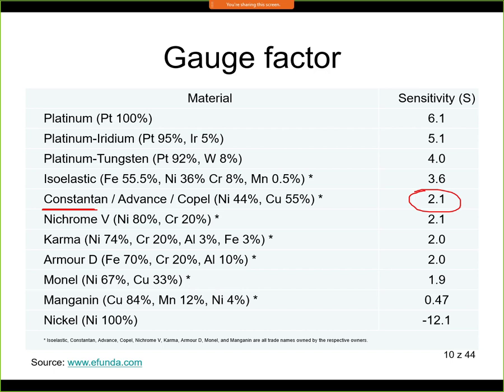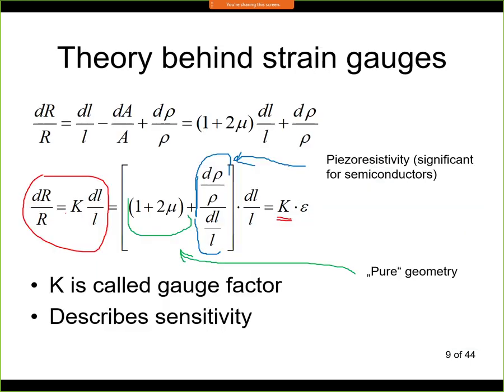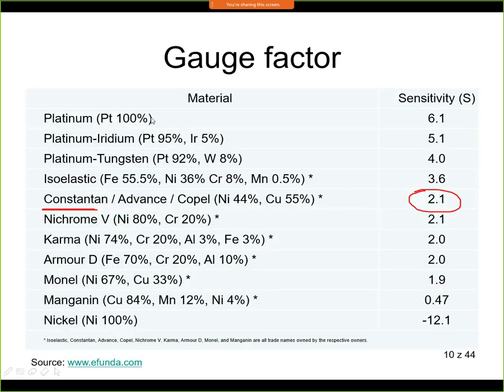it is not. The reason is that platinum has a significant temperature coefficient of resistance. So in other words, a platinum sensor is a good temperature sensor, but the temperature is changing the resistance. So if we have temperature changes, then we will not be able to measure force changes, because the change of electrical resistance from the force will be much smaller than the value created by the strain that we are looking for. So platinum is not an ideal material for strain gauges, and we are looking for a material that does not change its electrical resistance with temperature.